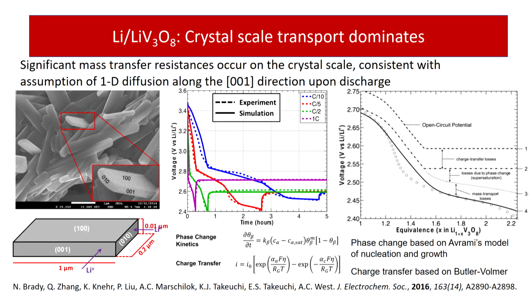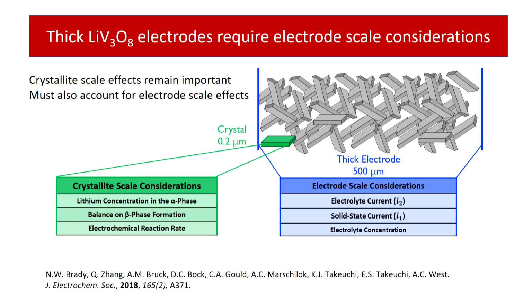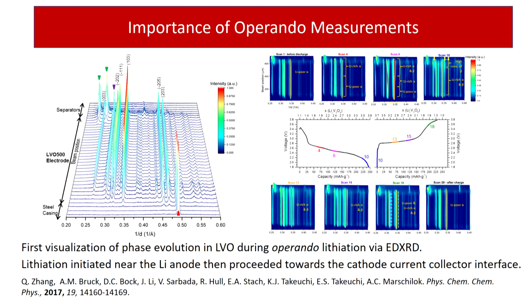If the electrode is thin enough, a lovely continuum model can be developed that just depends on the size of the particle itself. If we go to a thick electrode, now that's where the transport through the electrode becomes important. And by combining theory modeling with experiment, where we can actually monitor the phase fractions forming as a function of time to get spatio-temporal resolution, and combining that with a continuum model, we now have the ability to predict not only what's happening, but where.